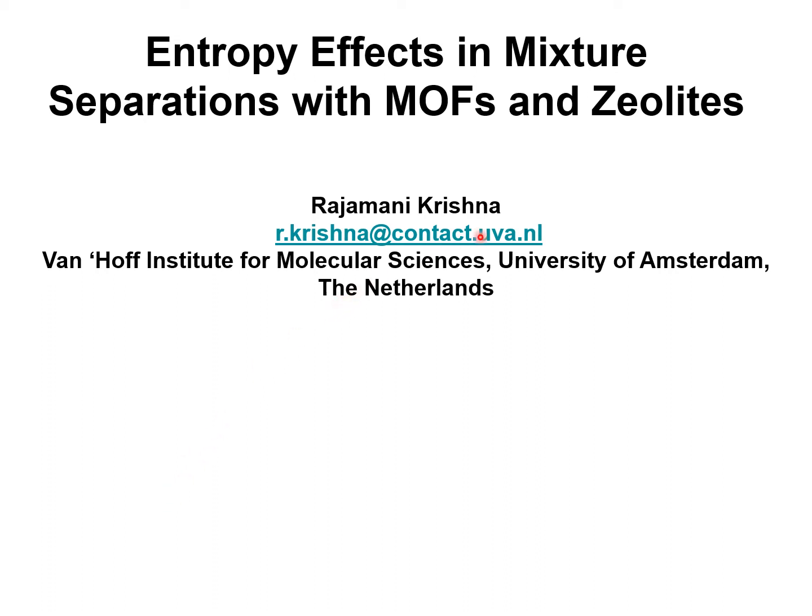For separations of mixtures with microporous adsorbents such as metal organic frameworks and zeolites under conditions in which the occupancies within the pores are close to saturation, the separations are dominated by entropy effects that rely on differences in the saturation capacities.